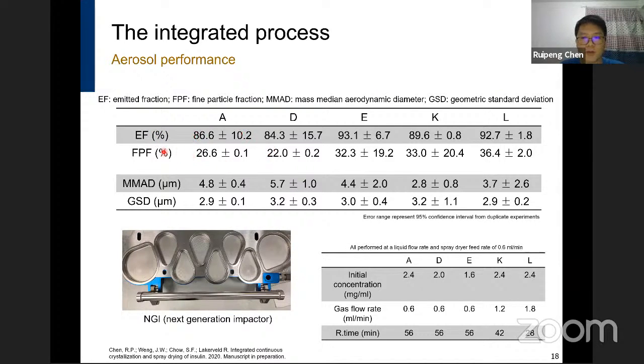While the FPF is in the range of 20 to 36%, which is generally considered acceptable for pulmonary drugs. But we observed a large variation for conditions E and K, for reasons that we don't know. For MMAD, they're around or less than 5 micrometers, and GSD is of the same magnitude as MMAD. So this suggests the particle size distribution is relatively wide. But in general, the insulin crystals obtained from the integrated process have promising aerosol performance, and condition L is considered optimal due to its good reproducibility and a high FPF.